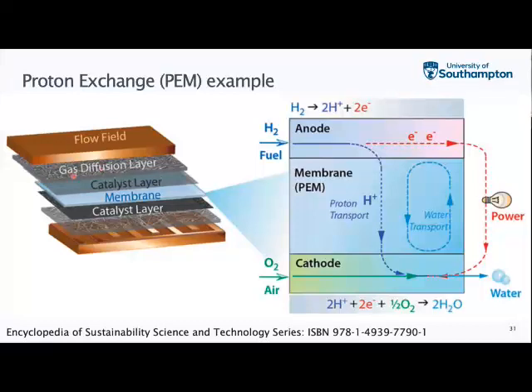Within the cell, you've then got a gas diffusion layer, which allows the flow of either the hydrogen or the oxygen, but doesn't allow the flow of any other species. And you've got a catalyst layer on the top of those gas diffusion layers, either platinum or other catalysts for the two reactions, separated by a membrane that then allows proton transport and water transport as the byproduct. And overall, you've got hydrogen coming in, ionizing to protons. The protons are going through that membrane to the cathode, where they're reacting with electrons and oxygen to generate water, and power is generated on the external circuit.